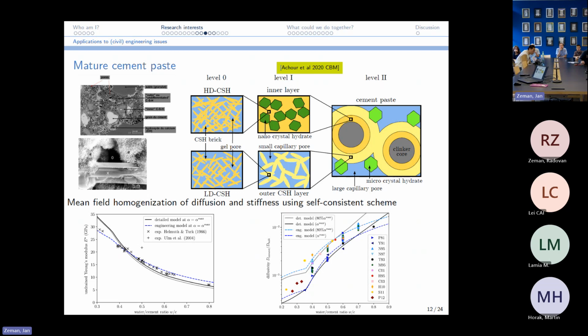It's not so easy to describe the microstructure of a cement paste, and just to zoom on cement paste, which controls the response of concrete, we've already had to put three levels or three size scales. So here's a micrometer on the right and nanometer on the left. And so you have to bring some information to your model, which is what is, say, the Young modulus of each of the constituents. And you have literature data on that. Give some information about the shape that you use to represent the constituents, either a sphere or some elongated or flat particles. And then what are the volume fractions of each of the constituents,